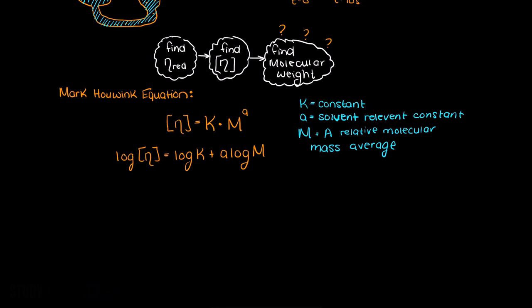This is called the Mark-Houwink equation, and as you can see here, it is of the form of an equation of a line in slope-intercept form. The constants K and a are the ones I mentioned earlier. From this Mark-Houwink equation, we can easily determine the molecular weight of a polymer if our two constants are known and the intrinsic viscosity over various concentrations.